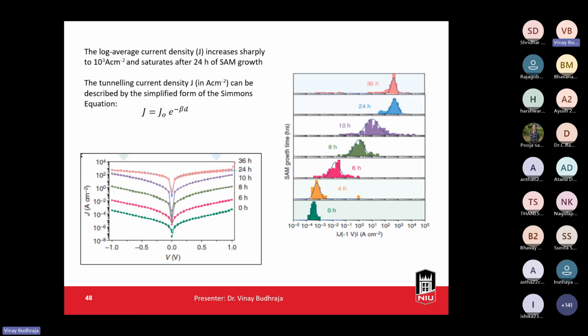In this figure, they measured the tunneling current density and SAM growth time. The log average current density increases sharply to 10 power 3 and saturates after 24 hours of SAM growth. So the self-assembled monolayer has been grown at different times in the processing.